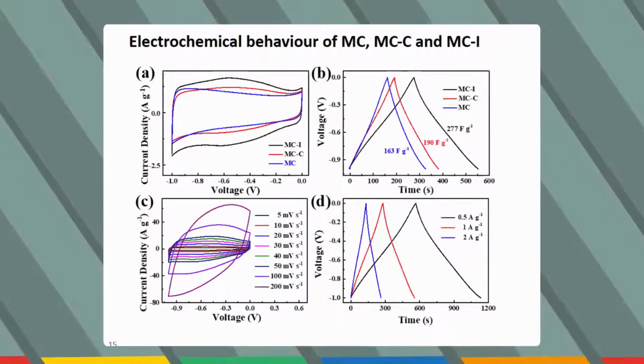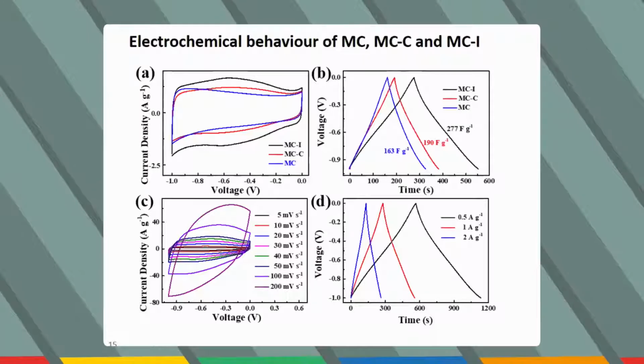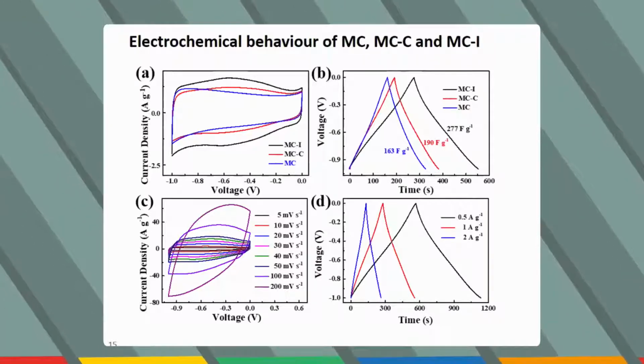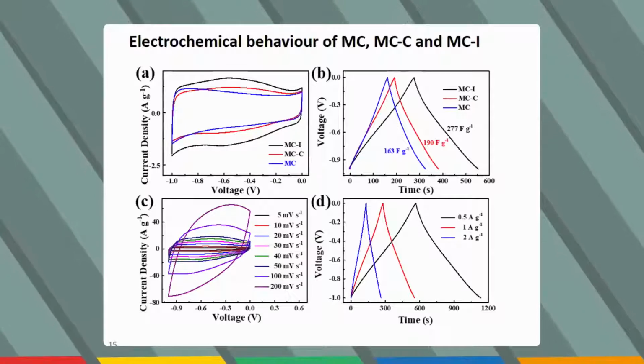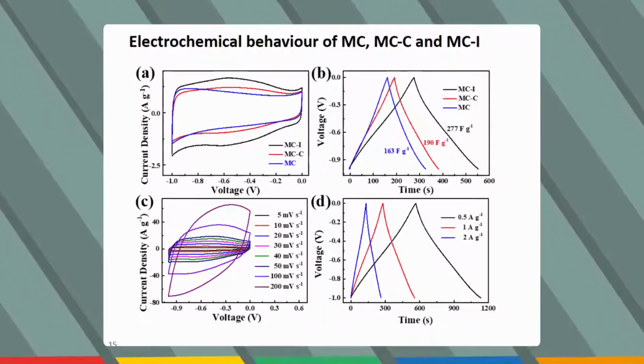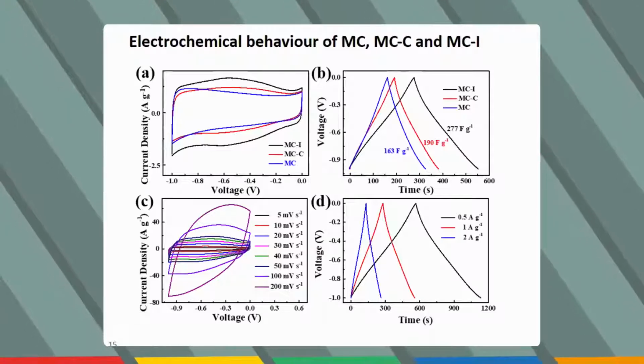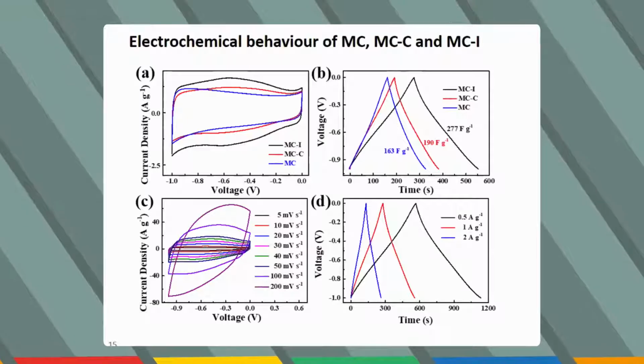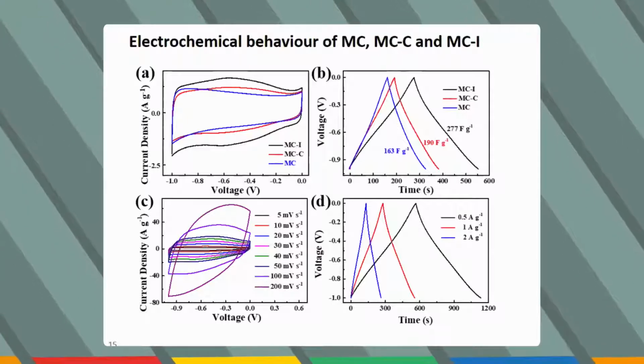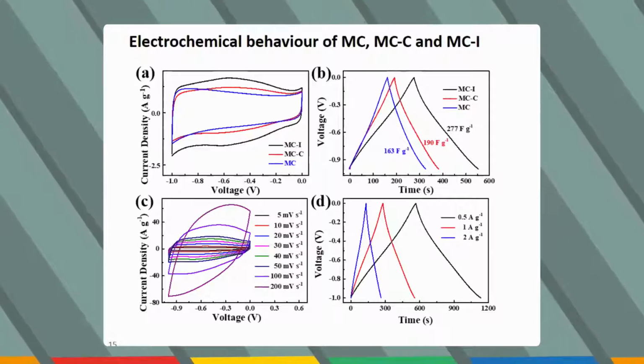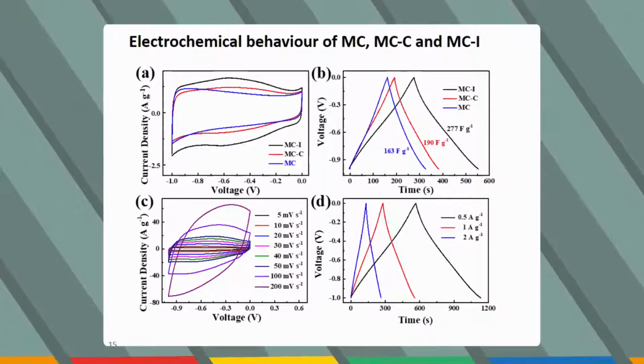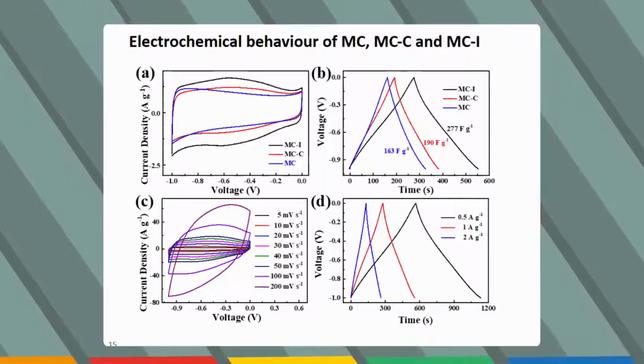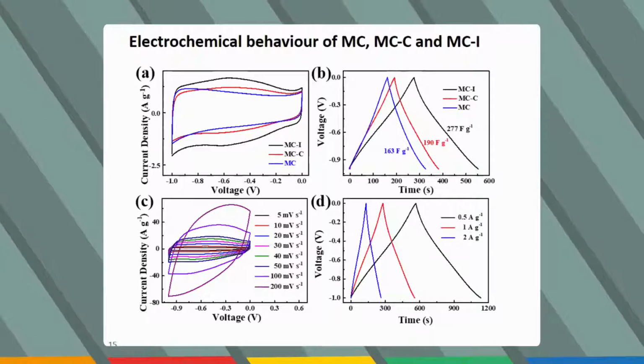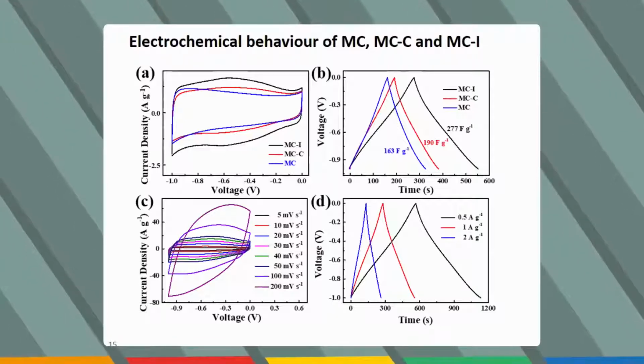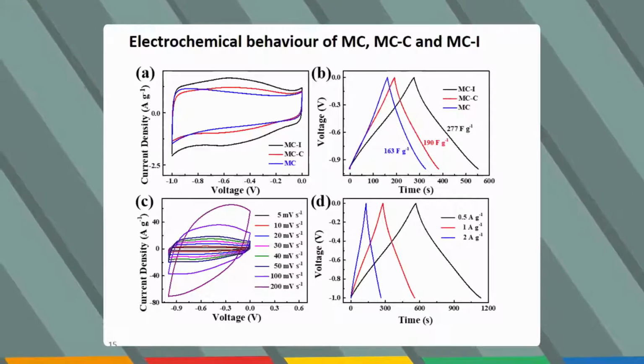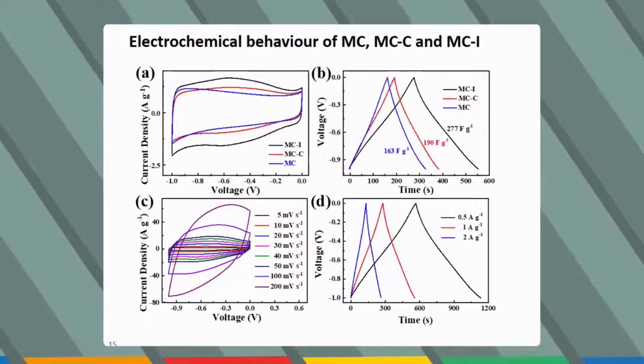We also did electrochemical tests of these materials, and we can see that for the mesoporous carbons with ionic liquids, we had quasi-rectangular cyclic voltammograms with very good area, showing a very good supercapacitance storage ability. And we also did GCD, which is charge-discharge measurements, and we can see that there is a very good reversibility during charging and discharge.